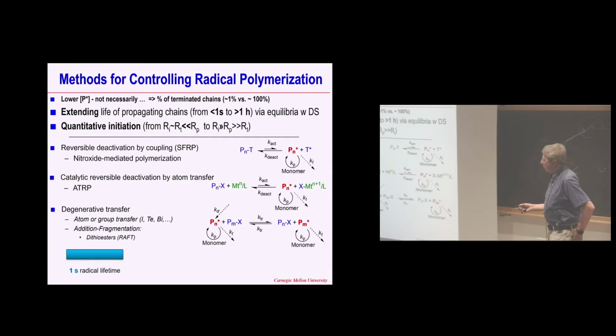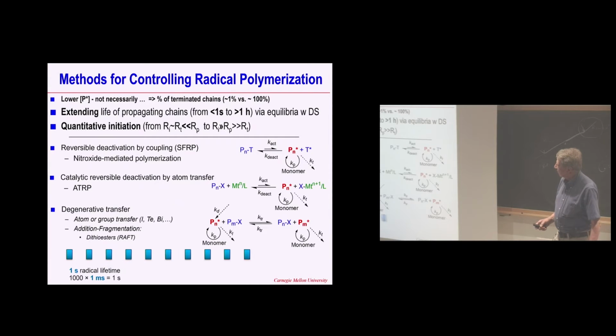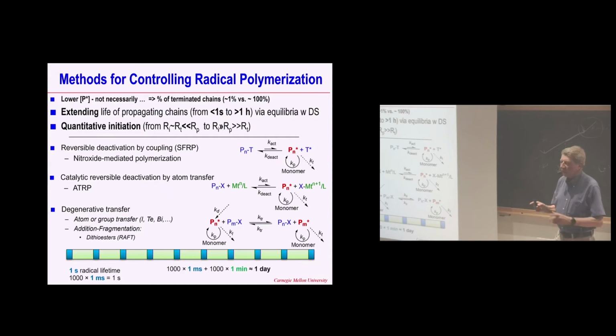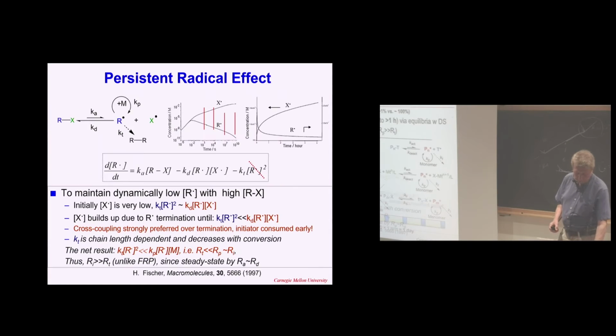So here, if you look at this process, you take really 1 second life of a propagating radical, and you chop it into 1,000 pieces, 1 millisecond each, and then insert between every millisecond 1 minute dormancy state. So this 1 second is still 1,000 milliseconds plus 1,000 minutes. So it's a day. You have enough time to really make very fancy, sometimes molecular architecture.